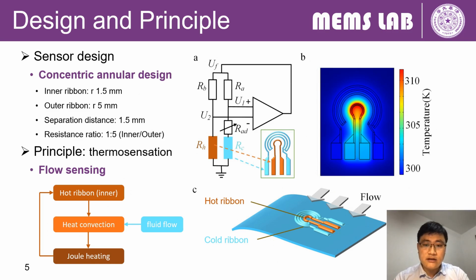As shown in this figure, the sensor has two concentric annular thermosensitive ribbons, the inner and the outer ones. While working, the inner ribbon is Joule-heated and is therefore called the hot ribbon. Joule heating generates a convection heat transfer to the surrounding fluid. The fluid flow increases the convection heat transfer, which will increase the Joule power of the hot ribbon to keep constant temperature. So, the hot ribbon works as a flow sensor using Joule power as an indicator of flow velocity.